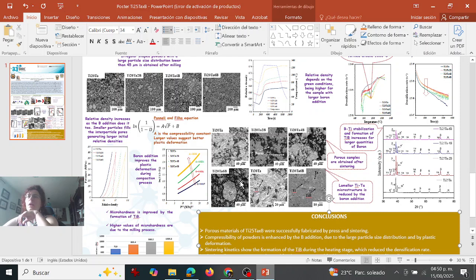All right, let's have a look at these images for the different samples. Titanium 25% of tantalum, which means no boron addition. In here for the 2% of boron, in here 4%, 6%. And here we observe that the porous samples are obtained after sintering. If we have a look in here, we will see different pores with different dimensions.